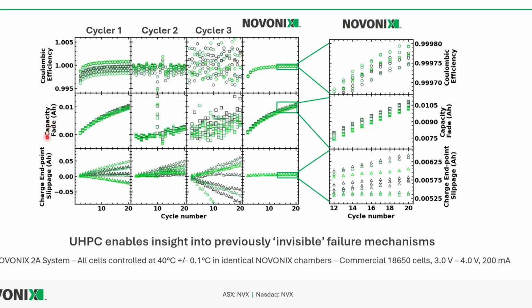For something like capacity fade, this is something that's cumulative over many cycles. And so you can see no matter what cycler we put it on, no matter what the resolution is, eventually we get that trend where we can see the capacity decreasing, or in this case, the fade increasing over time. And we use these metrics all the time. Why slippage isn't a very common metric is because it just isn't possible without that really high precision and really high accuracy. And you can see here that this slippage that we showed in the previous slide was very consistent on the Novonix system, but on all these other systems, we're walking forwards in capacity, we're walking backwards in capacity.